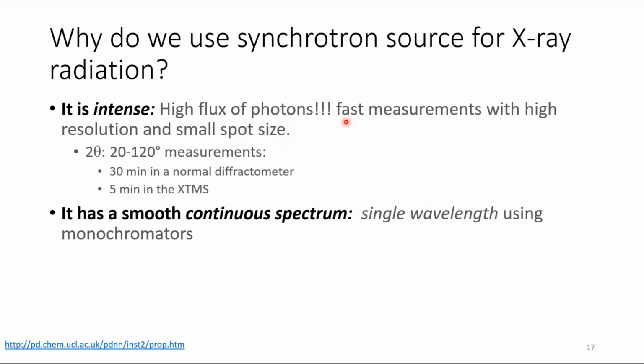So that allows you to make fast measurements with high resolution. You are going to see much more details in shorter times. As an example, I have here a 2 theta space, let's say between 20 to 120 degrees. You are going to conduct this measurement in a conventional diffractometer, and there you are going to spend like 30 minutes. If you have a high energy synchrotron, you are going to spend 5 minutes or less, probably 1 minute. And this is the difference.